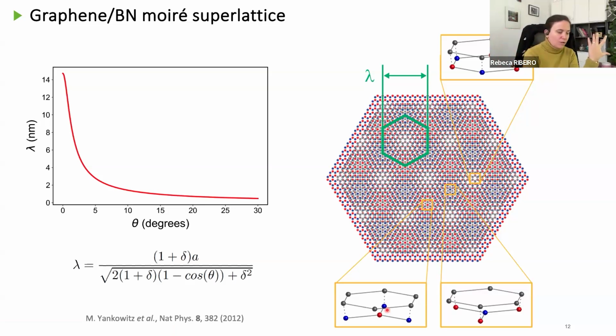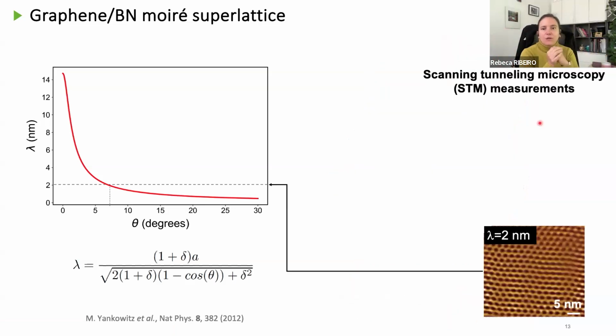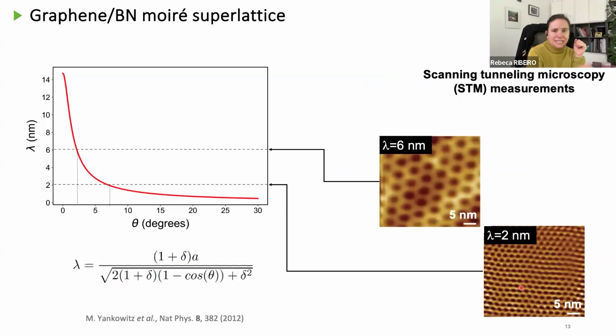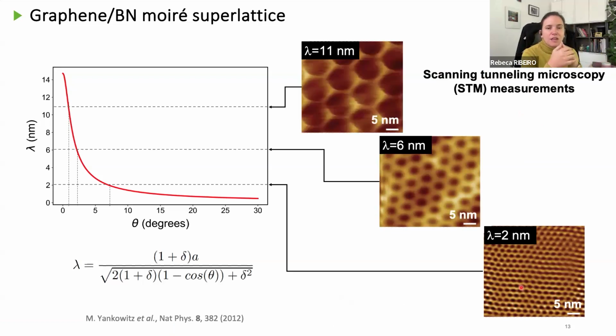However, it's not the whole story. If you look with STM, so if you do STM spectroscopy, or scanning tunnel microscopy, sorry, what you can observe is that depending on the crystallographic orientation, you will recover moiré of different sizes, as I told you before. But after certain alignment, you recover a structure that is a little bit different. You can already see, for example, that the structure at 6 nanometers and 2 nanometers moiré is not exactly the same as the one at 11 nanometers moiré.